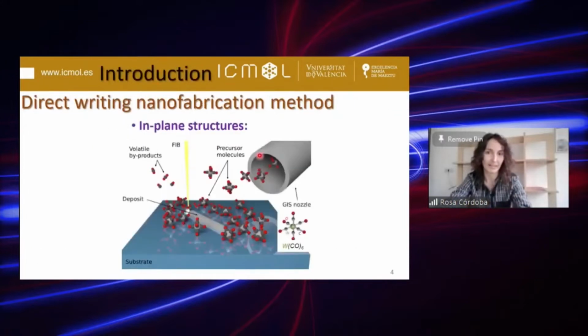So how can I create superconducting nanostructures in plane and out of plane, three-dimensional? This technique is called focused ion beam induced deposition. This is a general sketch for the in-plane application. In this specific case, we use tungsten hexacarbonyl as a precursor molecule, and this molecule is delivered from this gas injection nozzle. These molecules are adsorbed on the surface, and the focused ion beam partially decomposes them, creating a deposit in the plane.